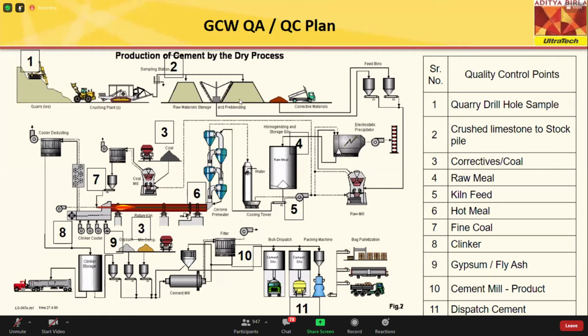This clinker, along with gypsum and fly ash, is again ground in the cement mill. Here also we do a quality check for cement, and then finally, during the dispatch stage, we monitor the quality of cement. Now at all these stages we monitor quality round the clock, because it is a process, so we cannot depend on a single sample, but have to check quality around the clock.